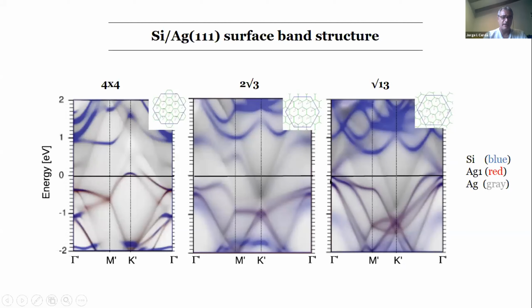First, I'll show you the band structure we have here. It's a kind of awkward band structure. I calculated it with the Green's function method, so the surface is totally semi-infinite, and we have a real continuum of bands. We can do projections on different atoms. Here I'm putting in gray the projection of the substrate, in red the projection on the first silver layer, and in blue the projection on the silicon atoms. So as we see, a continuum of bands. When we have these marked edges, it's that we typically have band edges of the bulk band.